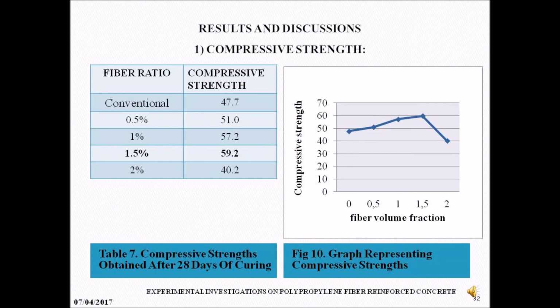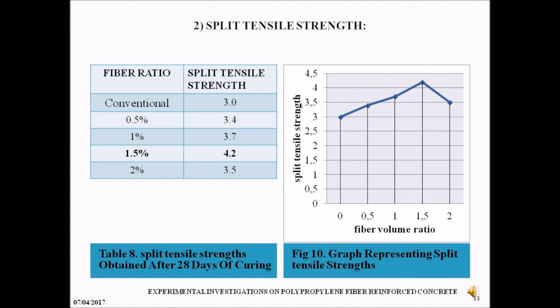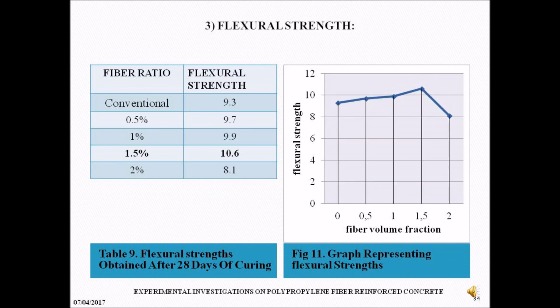Results and discussion. First, compressive strength. From the graph, it is shown that 1.5% showed maximum result and after 2% the strength is gradually decreasing. Number 2, split tensile strength. The graph is plotted for split tensile strength against fiber volume ratios. 1.5% shows maximum strength, whereas at 2% the strength is gradually decreased. Number 3, flexural strength. 1.5% ratio shows the maximum strength and as usual at 2% it is gradually decreasing,